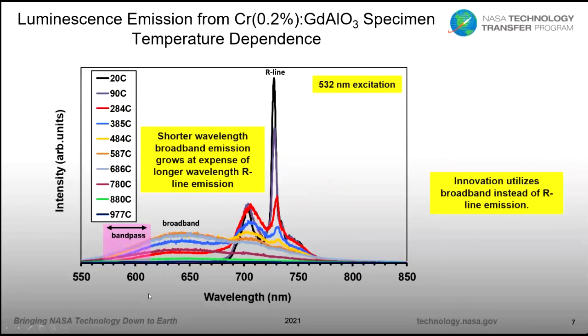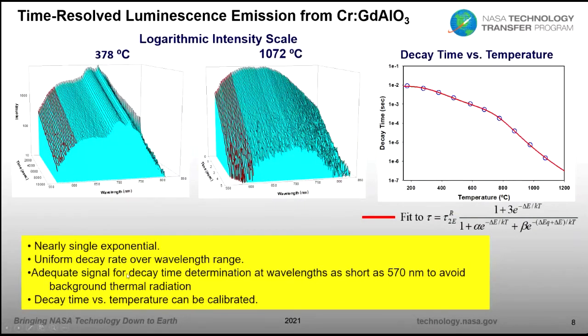Now here I show how the emission bands decay, comparing the spectra as they decay for two temperatures. We excite it with a laser pulse, not a continuous one, and then we watch how the emission band decays after the excitation pulse is turned off. At both 378 degrees C and 1072 degrees C, where intensity is plotted on a logarithmic scale, we see pretty straight lines. Plotted on a logarithmic scale, a straight line means you're close to a single exponential decay.